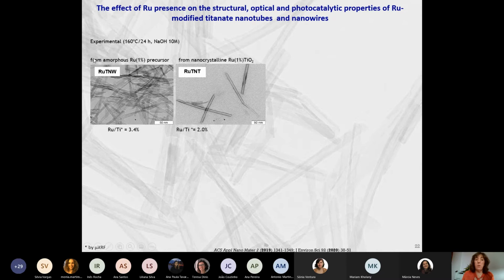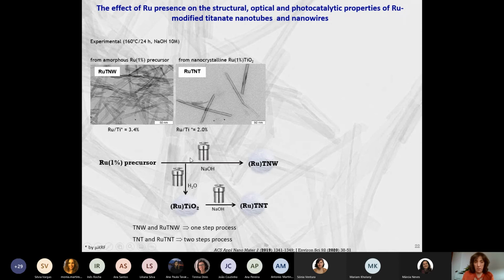Well, let's see. We start to prepare a precursor with 1% of ruthenium, and then we decide directly to prepare ruthenium titanate nanowires here. Using exactly the same precursor, we first prepared TiO2 with the ruthenium, and then prepared the titanate nanotubes that are here. Well, as you can see here, the amount of ruthenium that we have is different. Why? Because we are using the same precursor. Well, we lose some ruthenium because we have a two-step process, and that's why we lose some of this ruthenium.